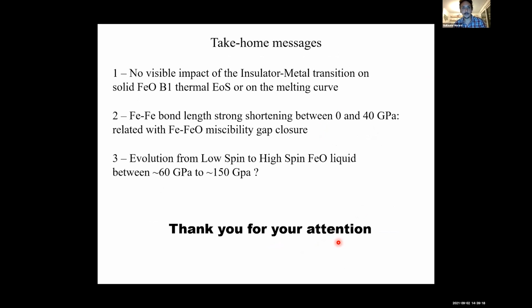Just to wrap up, we didn't see any visible effect of the insulator to metal transition in the solid B1. We have this Fe bond length shortening, which could be linked with the shrinking of the miscibility gap, and potentially this evolution of the intermediate spin in this 60 to 150 GPa pressure range. So thanks a lot for your attention.